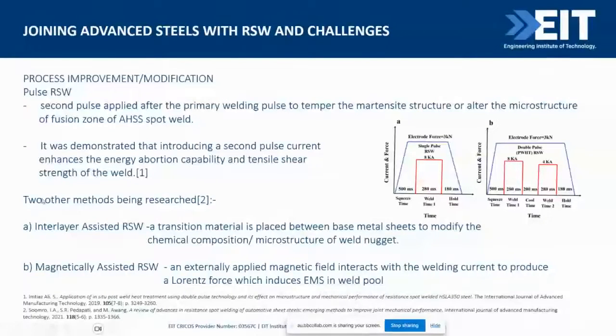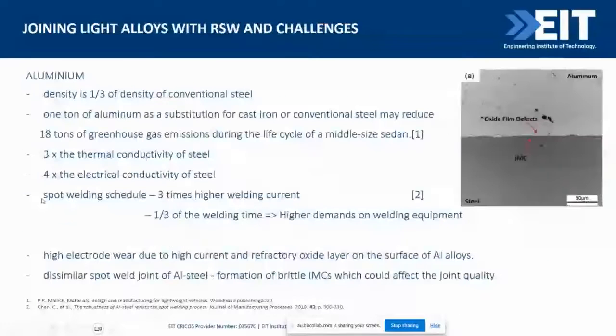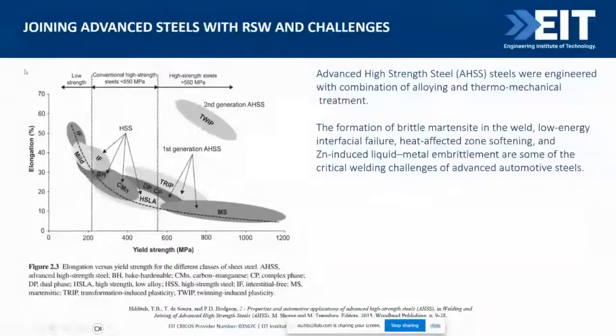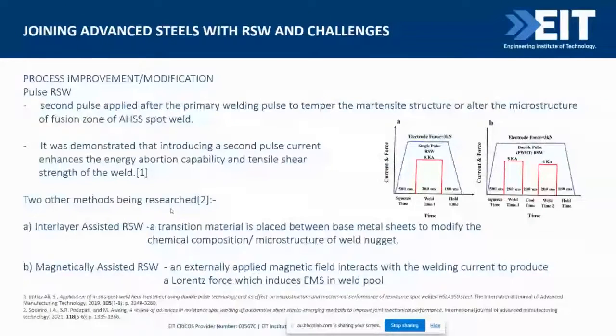Now that is on advanced high strength steels. So the advanced high strength steels are steels which have got yield strength anything greater than 550 megapascals. So the issue with this is because they are highly alloyed, they've got a very high carbon content. When you heat them up, they become hard and brittle. So they don't give you the required pull-out weld. Even though they're strong, they will naturally fail via interfacial failure. Right?